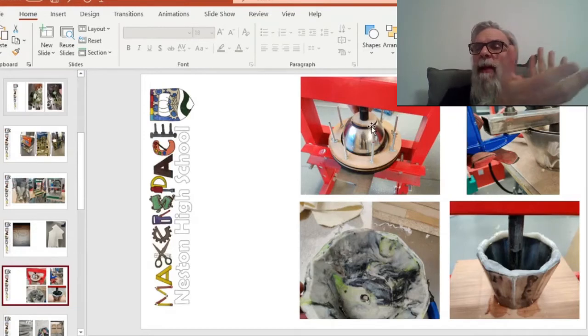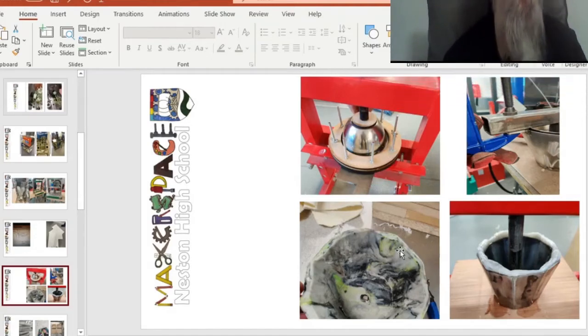I started speaking to Brothers Make, and Matt from Brothers Make, we started really chatting and talking about things. He said, maybe you have to heat your mold up. So I tried that, heated the mold up, and it seemed to work better. Then I spoke with Arthur from Plastic-Tastic, and he said, maybe look at your clamping pressure. So we added more bolts around the actual ring. It improved it, but then we got to the point where we didn't like the outcome from the bowl. It came out quite nicely, so we had a small bowl that came from it.